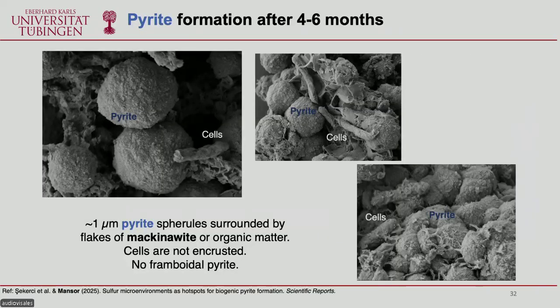And how does the pyrite look? Well, after 4 to 6 months, we see a lot of these structures. These pyrite are very, very small. They're about 1 micrometer in size, and they all look more or less like spheres that can be surrounded by very small crystals, maybe mackinawite, and some organic matter. We don't see any cell encrustation, and we don't observe any framboidal pyrite after 4 to 6 months. Okay, that's good.